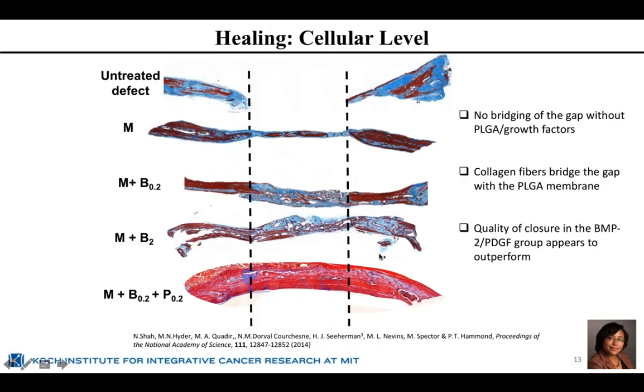But it's only when we look at the actual histology of the bone that we see the impact of introducing the dual growth factor system in which we have staged release. So here we have a membrane that was placed across the cavity, and all of these are histological slices in which we can see the bone margins on either side, a critical defect that did not heal in the untreated case. With just the membrane, we get a collagenous membrane that is generated across it, but no true bone. We do get very nice solid bone generated at 0.2 micrograms, and at 2 micrograms, we see even more deposition of bone. The problem here, though, is that we see a lot of defects in the bone, lots of gaps, but also roughness along the edges.